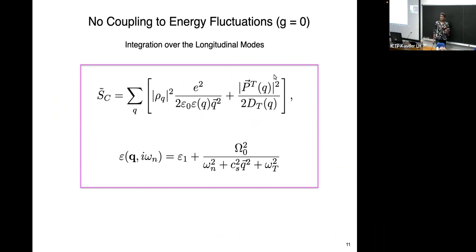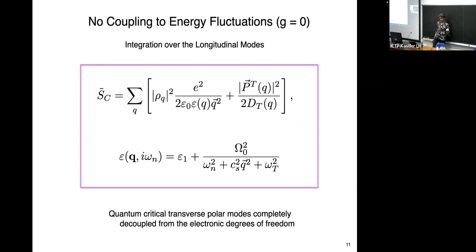So let's start simply. Let's take G equals zero, no coupling. If we take G equals zero, we integrate over the longitudinal modes, and what we have here is our dielectric constant, and the dielectric constant that we're going to put in is going to be only ionic. Once again, we see that the quantum critical transverse modes are completely decoupled from the electronic degrees of freedom, and once again, this is why we don't need to invoke energy fluctuations.